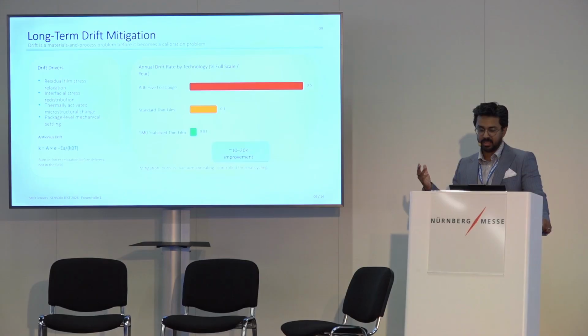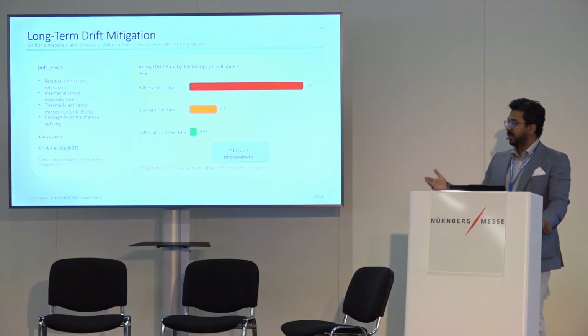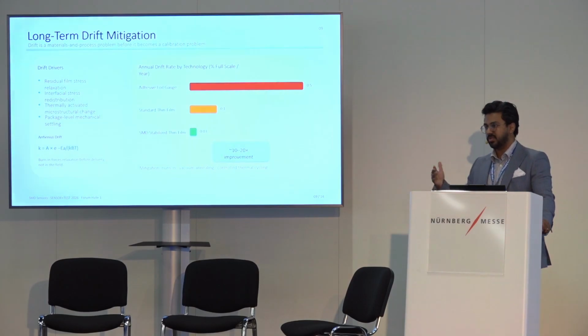Just to mitigate that residual film stress, what can be done is before sending out these sensors, you can anneal them in-house. You can deliberately vacuum anneal them in the factory, and age them and calibrate accordingly. If that process exists, it eliminates the residual stress that appears over a long period of time. So when designing the sensors, you must keep in mind that these drivers are super important, and that has to be established in the manufacturing stage in quality, and calibrated and certified according to certain standards.